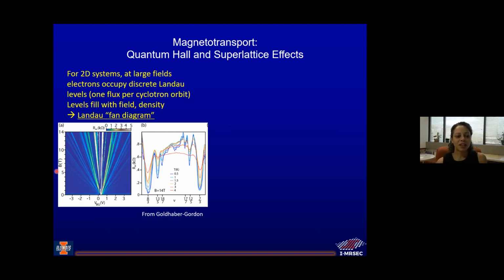Okay, so on this plot on the left, these bright lines basically show, I believe, the low resistance lines. These are in between the filled Landau levels, and then these darker blue lines are the Landau levels. And what you see is that they start at some value, and then as you increase density or increase magnetic field, they start filling linearly with either field or density. Okay, so here's what you see from a Hall effect. You get a drop in edge resistance when you don't have a filled state, and increased resistance when you have a filled state, and then this fills linearly with both field and density, which you see here. And so that's this Landau fan diagram, which tells you that you have a quantum Hall effect and Landau levels.